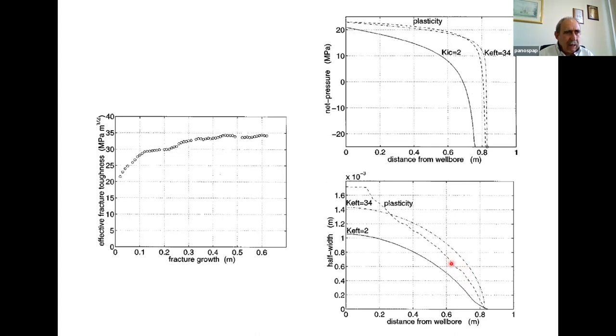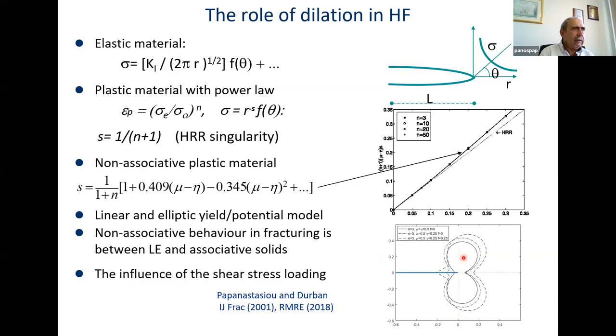The reason is because the model we used was fully dilatant, which means that the dilation angle in the plasticity model was equal to the friction angle. In reality, the dilation is lower than the friction angle. So if we had plasticity with dilation lower than friction angle, non-associative plasticity, as we call it, I believe the result will be closer. And we tried with some analytic work to look at also the influence of the dilation, of non-associativity. And we found that the non-associative solution is between the elastic solution and the solution we get for associative solids. So the non-associative is in between.